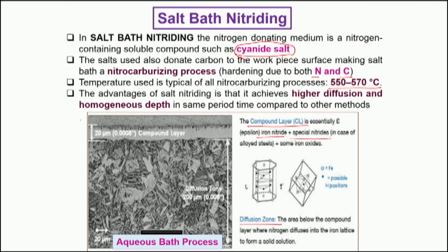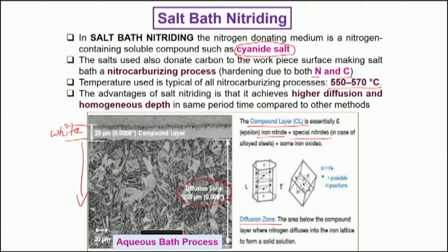The real-time microstructure shows a compound layer — the so-called white layer — and then below it the diffusion zone. There is a clear gradation of microstructure: not only does the amount of nitrogen vary with depth, but also the identity and crystal structure of the phases vary. This white layer is an extremely hard layer — about 10 micrometers or even less — with hardness as high as 70 HRC.